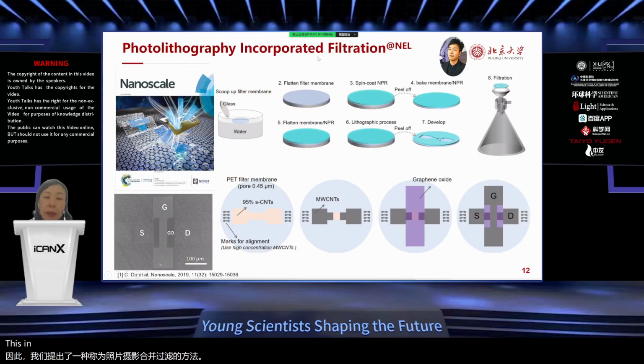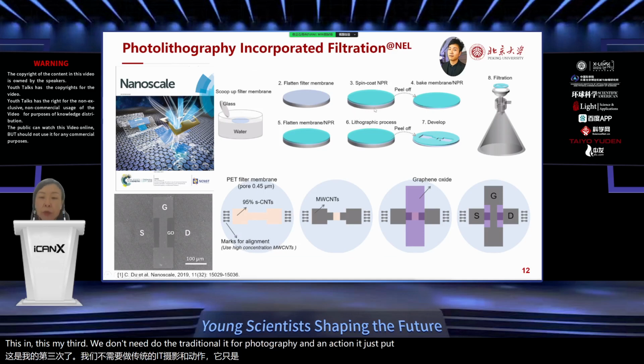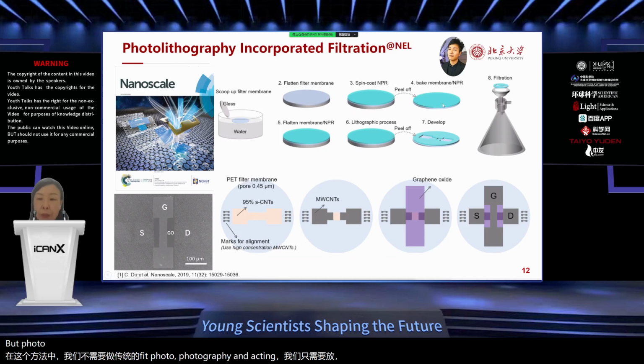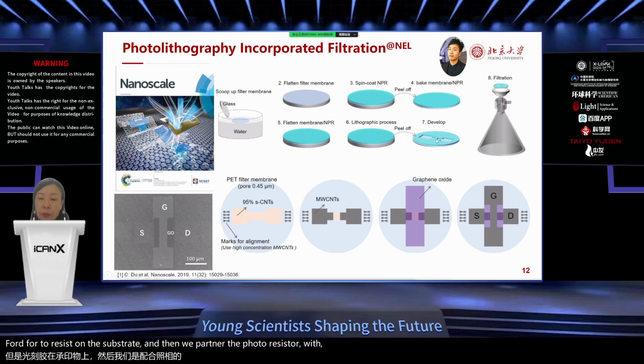In this method, we don't need to do the traditional photolithography and etching. We just put the photoresist on the substrate, and then we pattern the photoresist to form the expected pattern, and then we peel off this photoresist and stick it down. Peel off this photoresist with the PET substrate.